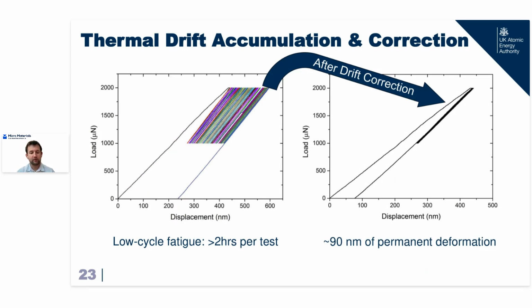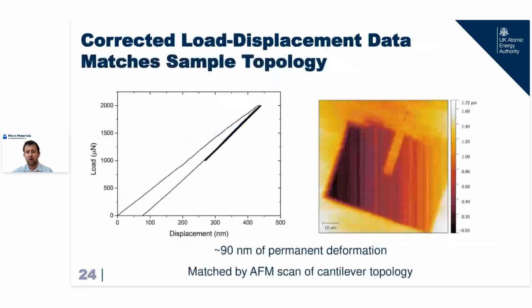Actually, the micromaterials system is extremely stable, and thermal drift rates are low enough that a simple thermal drift correction after the test collapses most of this load unload low cycle fatigue behavior on top to a single curve. The drift corrected data only showed 90 nanometers of permanent deformation, which matches up very nicely when we start using the indenter like an AFM, taking this topological scan of our cantilever after testing. You can't tell within the color scheme, but you can believe me when I say the end of that cantilever is now only 90 nanometers below the surface.